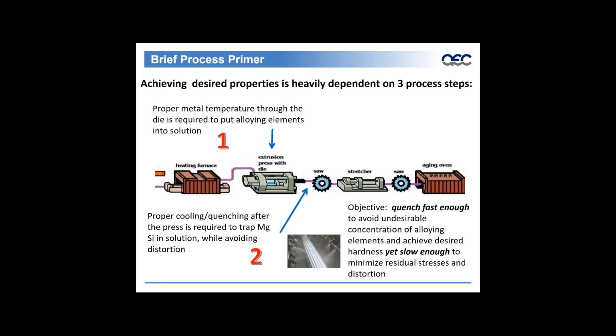As a result of the reduced amount of distortion, recovery rates are higher, downstream tolerances associated with profile cross-section, twist and bow are improved. As a result of the lower mag and silicon, the production rates are also higher as a result of the improved metal flow through the extrusion. So a 6060, a 6063 low mag, low silicon alloy would flow out of the press here at step 2 through an air quench and achieve the proper mechanical properties in T4 condition.